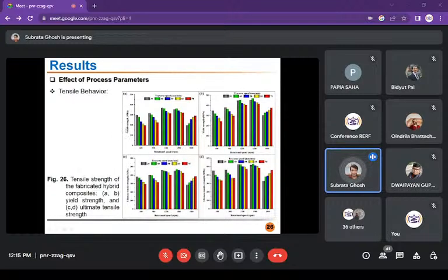Here is the typical graph between yield strength and rotational speed for the first pass, and this is the second pass. Here also are the typical variations of the UTS value with rotational speed for the first pass as well as the second pass. For 1200 to 1500 RPM, it shows better yield strength, and for UTS also 1200 to 1500 shows the better value. The second pass shows better results because the overall distribution is good.